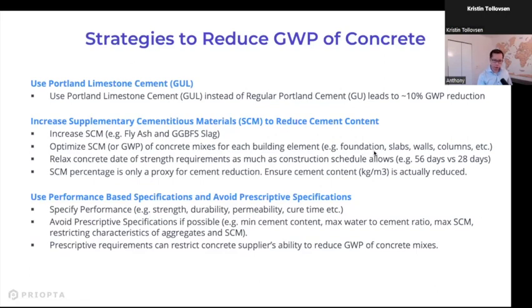So, for example, for your foundation, your slabs, your walls, your columns, for certain elements, you may be able to relax the concrete strength requirements. For example, if your foundation concrete is not a limiting factor for your construction scheduling, maybe you can afford to have those be 56-day mixes. So you allow 56 days for it to reach the strength that you need, instead of the typical 28 days. That will allow your ready mix supplier to give you a lower carbon concrete mix for each of those elements. So you want to optimize that for all the building elements. Where can you have higher SCMs? Where can you relax the strength requirements?